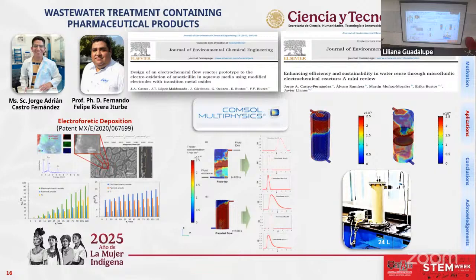And the most important thing was that we compared two methodologies. The first one was painting the electrode, and in the second one, we used electrochemistry to promote the electromigration of the ions over the surface, and we organize all the electrocatalysts better over the surface. And you can see here two graphs. The first one shows how the removal efficiency of the total organic carbon increases when we use the electrophoretic deposition in comparison with the painting modification.